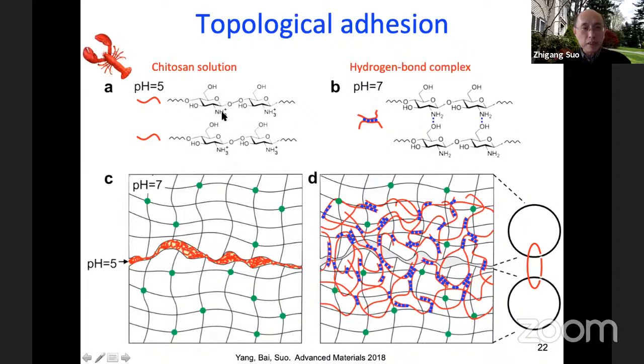The way it becomes a solution is when pH is low, you have a lot of hydrogen ion in the water, and that hydrogen ion attaches to this NH2 group, and makes it into an ion. And this ion essentially repels this ion, or however you think about it. It becomes essentially a salt. It's a polyelectrolyte, a salt with a lot of ions along the chain. That's pH equal to 5. However, when pH equals 7, the hydrogen ion is lost, and you have NH2 back. It's known that this NH2 and OH form hydrogen bonds. This hydrogen bond is similar to the hydrogen bond in cellulose, essentially in wood, the same kind of hydrogen bond. So all these things are known, including this pH control.